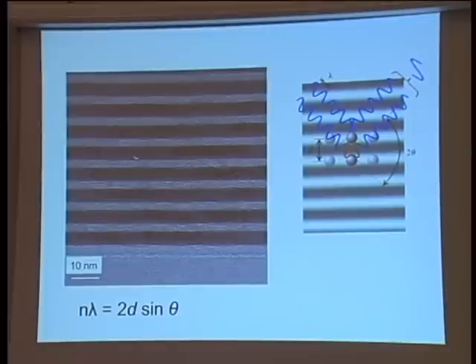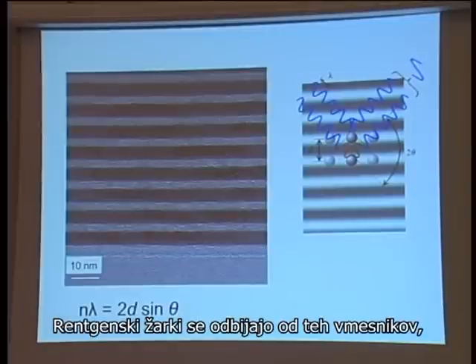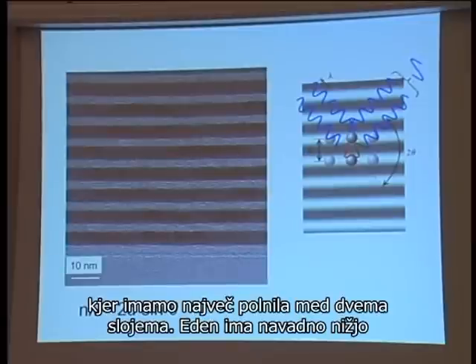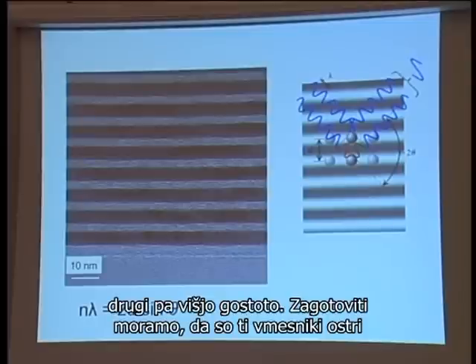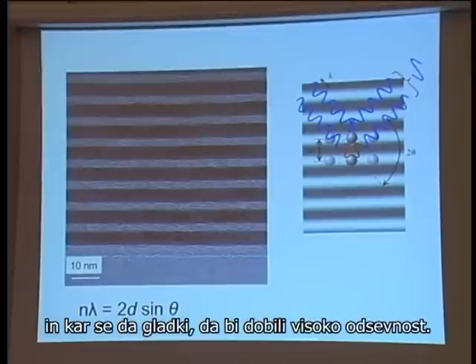And X-rays basically reflect off these interfaces where we have the largest gradient between the two layers. So one is usually lower density and the other one higher density material. And we have to ensure that these interfaces are as sharp and as smooth as possible to get high reflectivity optic.